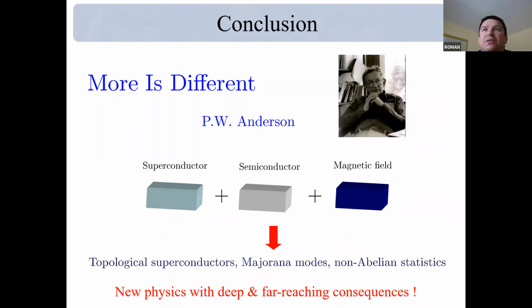And in both cases, you would expect the scaling with system length to be different from exponential. If you look at the supplementary material of the paper, there is a whole section discussing that. But the idea is that scaling with the system length tells you about the nature of these states. Either they are localized at one end, then the scaling will give you a constant. If they are gapless, then the finite gap will scale as 1 over L to some power, either 1 or 2. And we've checked for these scenarios.